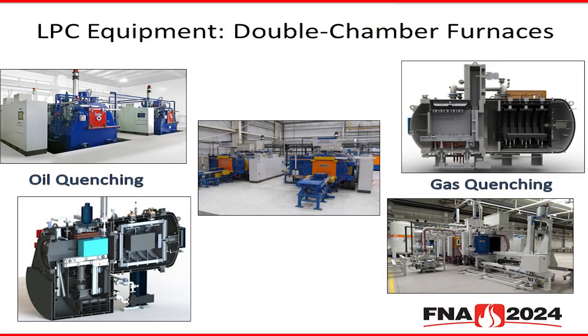And here you'll see a cross-section of both chambers. The other advantage to this is that we're holding this chamber at temperature at all times. So there's no wait for heating and cooling. It's just a matter of introducing the part here into the process chamber for LPCN, back out, quench, and out. So we can remain at temperature, saving some time in the process.